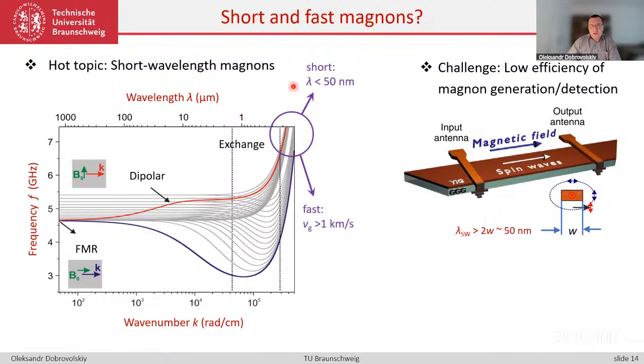So if you want to excite 50 nanometer long magnons in terms of their wavelengths, the width of the conductor should be of the order of 25 nanometers. And even with today's state of the development of e-beam lithography, technically you can have such a feature size in the fabricated antennas, but even if you use gold antennas, the sizes of the antenna become comparable to and even less than the electron mean free path in gold as a material.